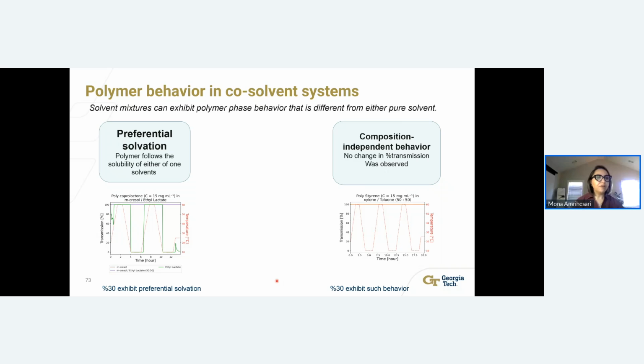30% exhibit preferential solvation, meaning that the polymer behavior is more matching towards one of the solvents and mimics that. So then we wanted to go back and see if the Hansen distance is important here, if the polarity is something that is dictating this behavior. These are all studies in progress, so I don't have anything more to share on the conclusion of whether any of these parameters are ruling this behavior. This is more thinking about the DOE design of how we can go from the binary system to a co-solvent system. The data is coming up, and you can find this information online in future from the Bukowala and Bredner Lab.